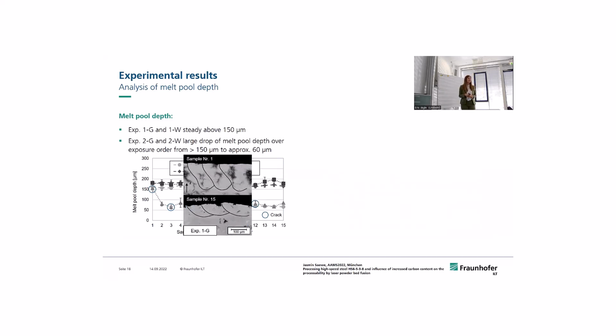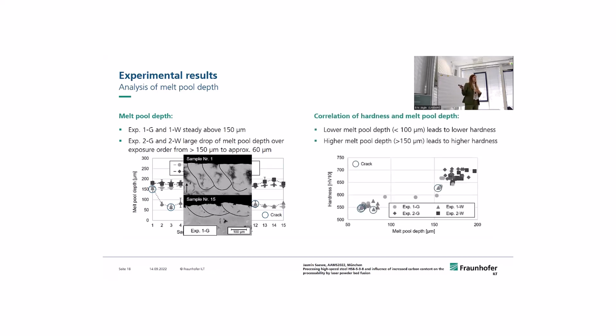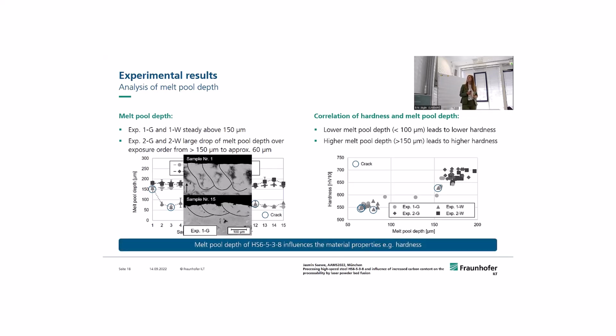Looking at the picture, it's very obvious. So same process parameters for all of those 15 specimens, and very high influence seems over the exposure strategy or the build position, the part position. I mean, that's a correlation of the hardness and the melt pool depth. You can see with smaller melt pool depth, smaller hardness, higher melt pool depth, higher hardness. Seems to be a little bit of a transition phase in between. But what we see is this material is very sensitive to the shielding gas flow, and therefore to process those kinds of materials, we need to have a steady shielding gas flow to be reliable and reproducible with our material.